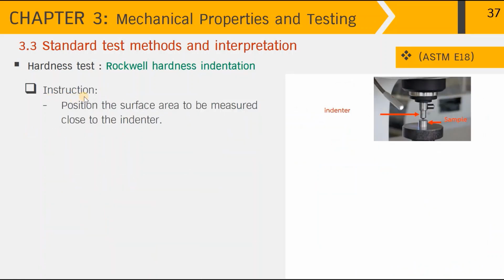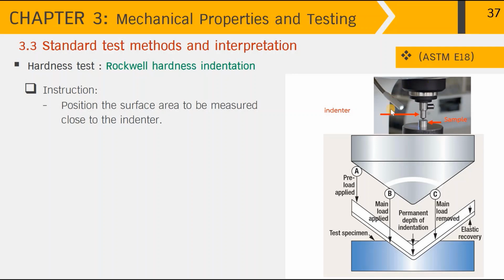And for the instruction of the test, we first have to position the surface area to be measured close to the indenter. Over here, you can see the indenter attached onto the indenter holder. The specimen to be measured is placed over here on the stage. And if I enlarge the view over here, you can see that on top of it is the indenter, and down here is the sample surface.